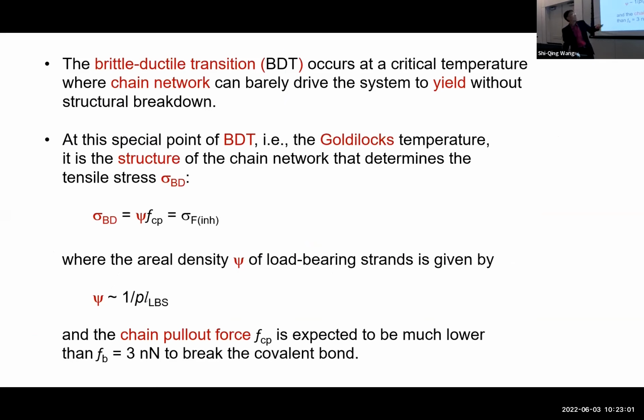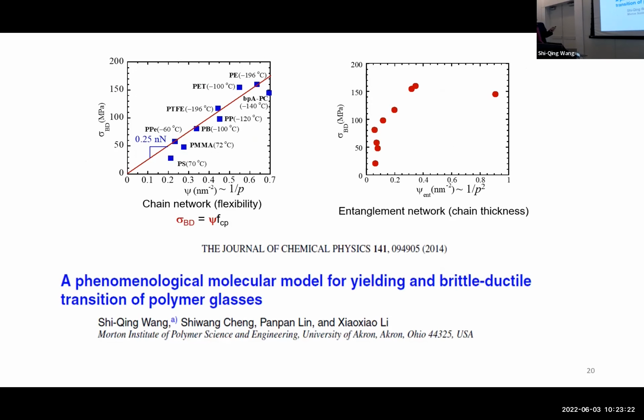So if you allow me to say, from this, I can even imagine how to calculate the stress. It will be just the load-bearing chains and the area density of load-bearing chains. And this gives me a notion of what would be the theoretical strength of my polymer provided by these two parameters. So if you fit this model to the experimental data, you find it offers some support of this idea of the fact that the strength of your material is dictated by the tension available in the chain before the network falls apart. And the way it falls apart mostly is through chain pull-out. So in any case, we have some idea about how much strength there is in a polymer.